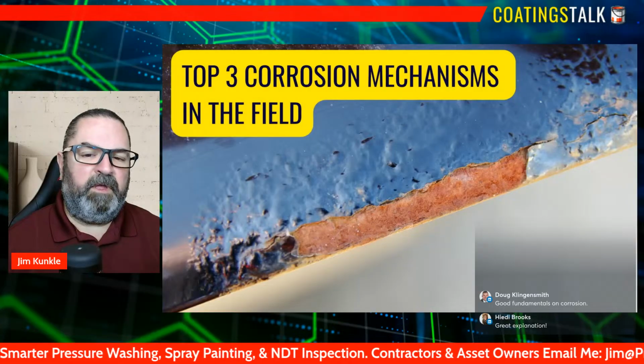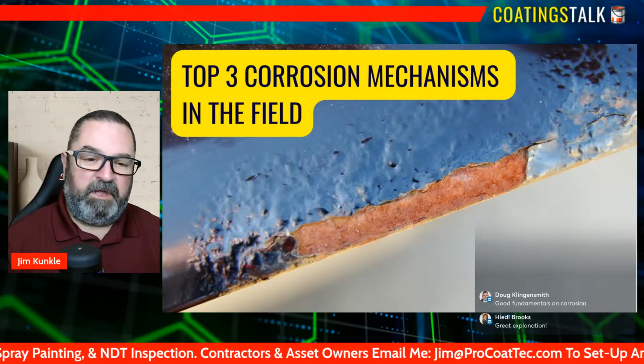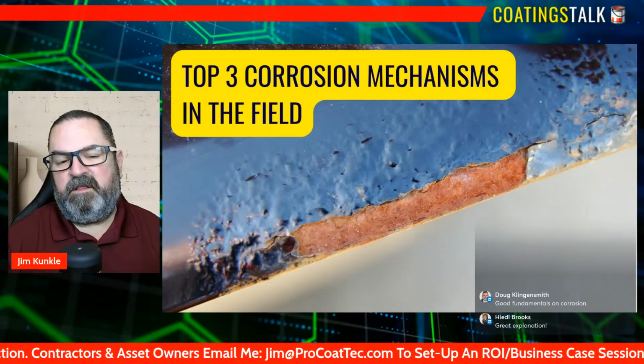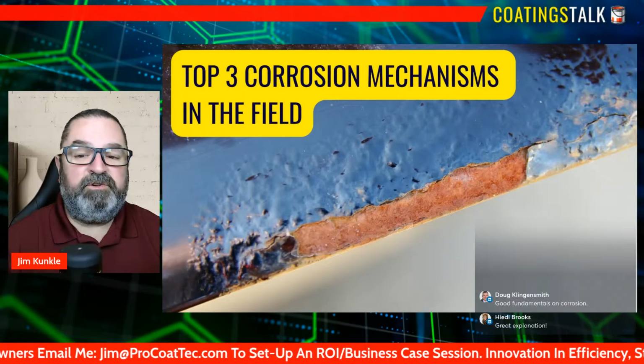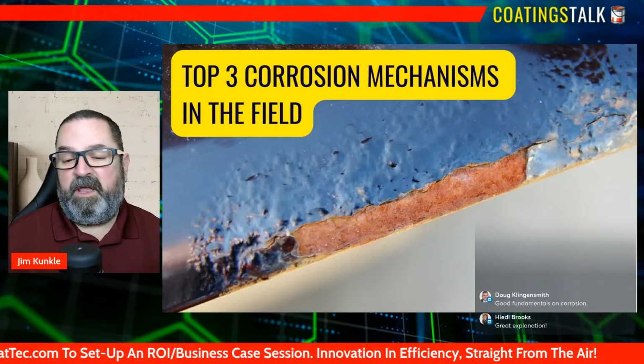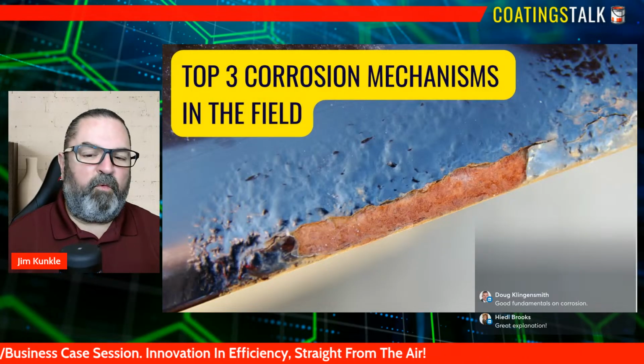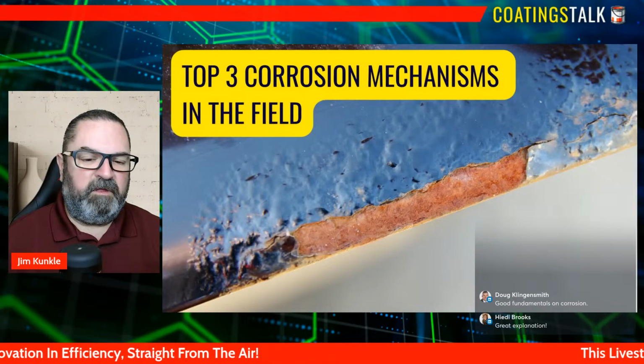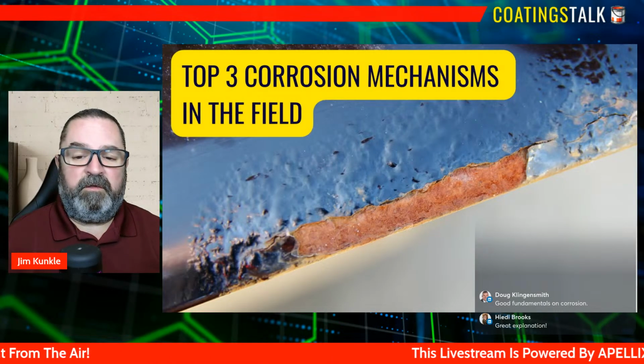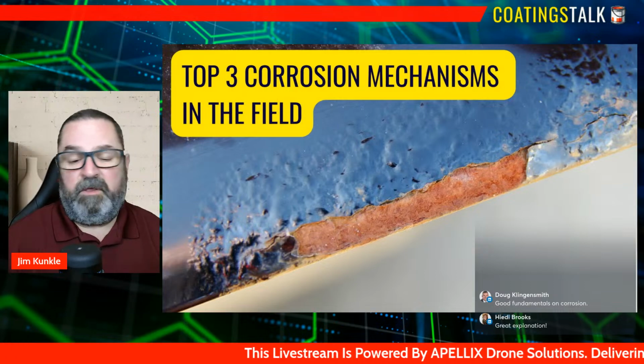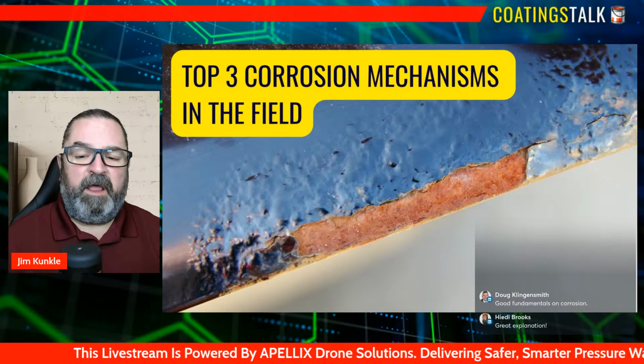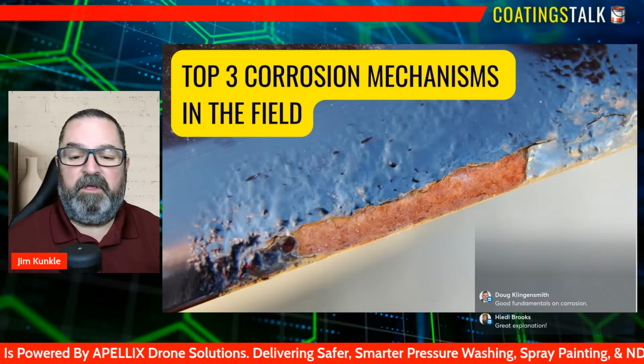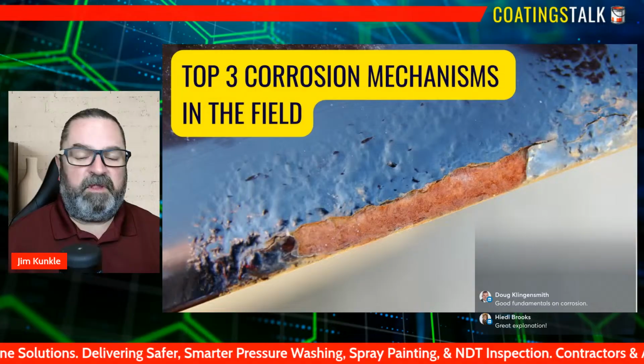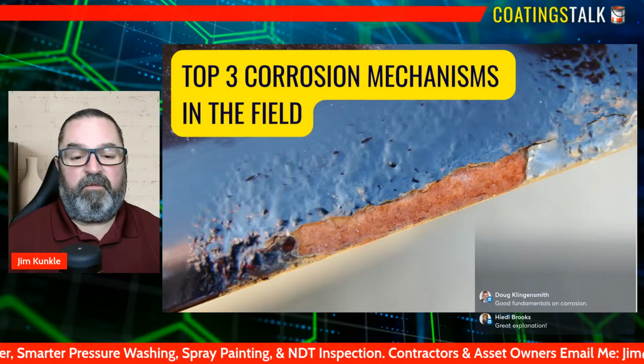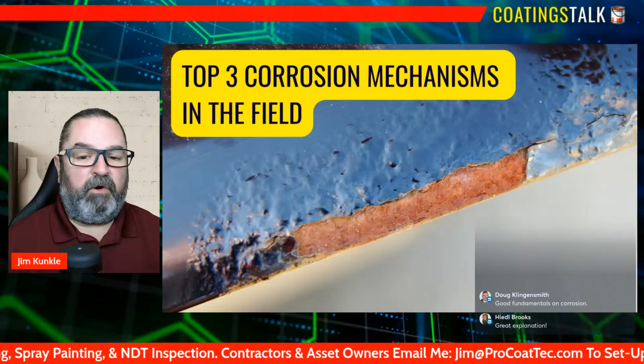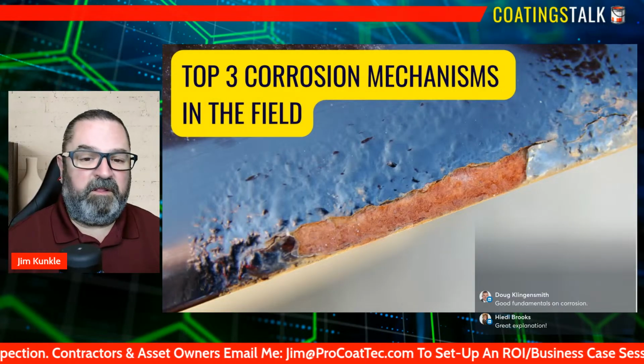What makes uniform corrosion particularly important for field professionals is its predictability. Because the attack is evenly distributed, it's possible to estimate corrosion rates, forecast remaining life, and plan maintenance with a high degree of confidence. But that only works where teams are actively monitoring surfaces and measuring thickness, instead of looking at it as normal aging. Assets can reach critical loss thresholds without anyone realizing how much metal has disappeared. The key is recognizing that even slow, steady corrosion adds up, and that early intervention through coatings, surface prep, and environmental controls really can dramatically extend asset life cycles.